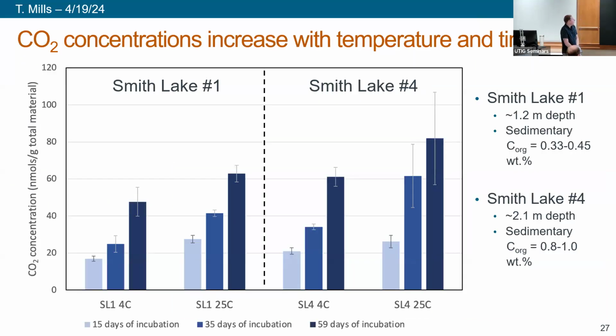Okay, so what we've seen so far with our incubation experiments is that CO2 concentrations are increasing with temperature and time. Just for reference, at Smith Lake 1, our sample comes from about 1.2 meter depth, and the organic carbon in this depth is actually really, really lean, 0.33 to 0.45 weight percent. And our Smith Lake 4 sample is from about 2 meters depth, and the organic content is about 0.8 to 1 weight percent total organic carbon.